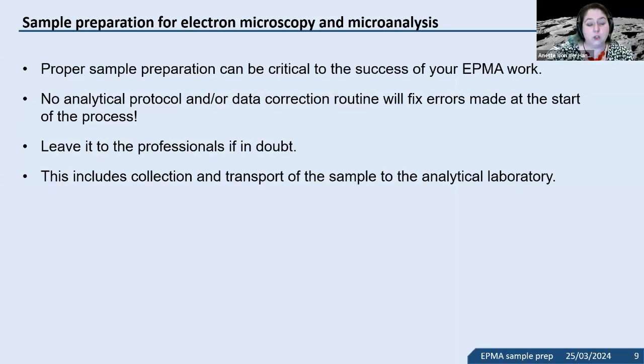But each spot will then be a reflection on your sample of how much surface roughness there is. Different minerals polish slightly differently, and different crystallographic orientations can polish differently. And so you get a very random, erratic data set, and wonder what's going on. Normalizing doesn't work. There are no magic things that can correct your data set when it comes to that. Usually I do think, leave it to the professionals.